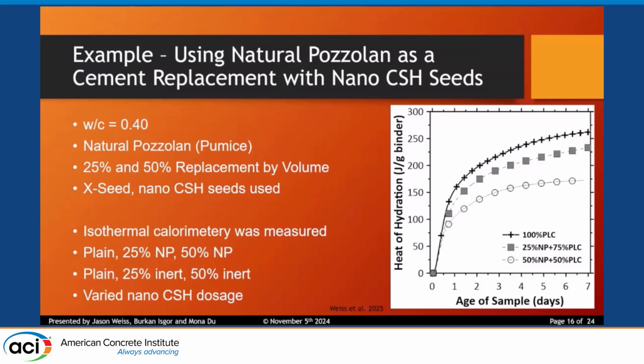Here I'm going to show you some examples. The first example uses a natural pozzolan, and we're going to put in some nano CSH seeds. It's a 0.4 water to cement ratio with a pumice natural pozzolan. I'm going to do a 25 and a 50% replacement of the clinker. I'm going to use a volumetric replacement because it has a different specific gravity than cement. If you just replace it by mass, you have more particles in there and you require more water to get workability, so your water demand goes up because you've got less empty space in the system. If you do a volumetric replacement and account for the water absorption of the natural pozzolan, it's amazing. The water demand is much, much lower.